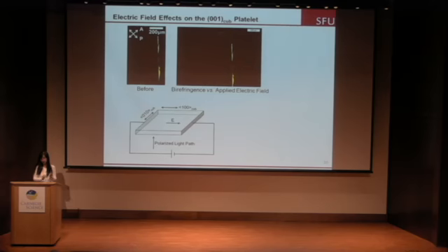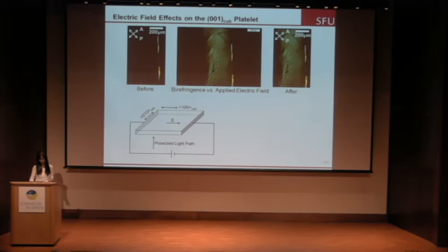But once we apply electric field, the sample becomes brighter and brighter. That means the birefringence is increasing. Because the nanodomains are perpendicular to each other before, but the electric field can reorient some of them, so they are not cancelled out completely now. This is how the sample looks at high electric field.